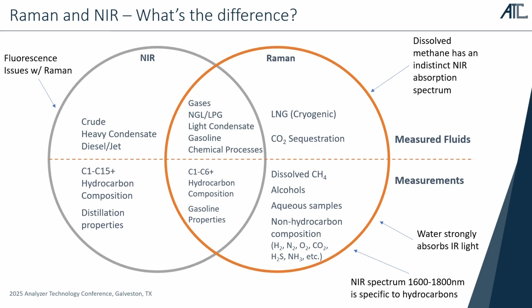Also, aqueous samples. Raman is the natural choice because water absorbs near-infrared light very, very strongly. So it can be extremely challenging to do an aqueous measurement with an NIR spectrometer. So Raman makes sense for something like an aqueous sample, like an amine CO2 scrubber. And of course, anything that's not hydrocarbons, Raman makes a lot of sense for, because there are a lot of common non-hydrocarbon molecules like hydrogen, nitrogen, and oxygen that are either not near-infrared active or very, very weakly near-infrared active. So it would just make a lot of sense to do a Raman measurement instead. Where you get overlap is measured fluids like gases, natural gas liquids, gasoline, extremely light condensate, and chemical processes. Those are kind of the things where NIR could work and Raman could work.